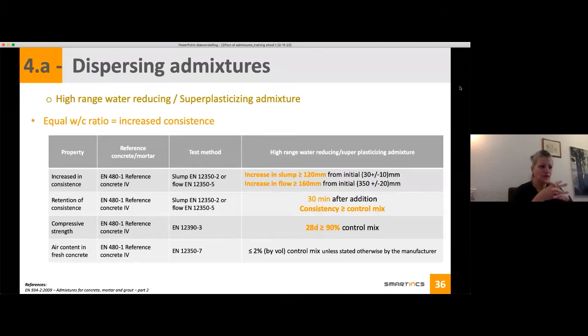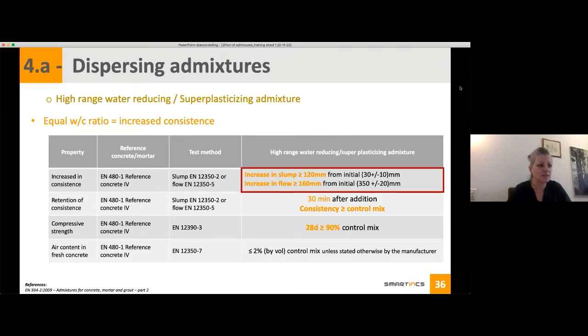They have a lot of effects, so they are classified by requirements. You have to assess them in two ways. First, you have to show that with the same water to cement ratio, which means that if you keep the same water to cement ratio, you will increase your consistency. So the first requirement is, okay, you have a reference concrete, and if you use the superplasticizing admixture, you should have at least an increase in slump of 120 millimeter compared to your reference.